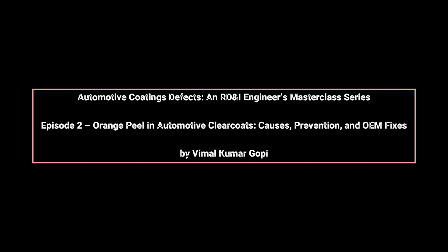Additives, such as flow and leveling agents, are often used to fine-tune surface mobility. Polysiloxane-based or acrylic-modified surfactants reduce surface tension gradients and promote flow, but they must be dosed very carefully, typically in the low tenths of a percent. Overdosing can create secondary defects like craters or fisheyes, while underdosing provides no measurable benefit. From an RD&I standpoint, additives are considered fine-tuning tools, not primary corrective measures.